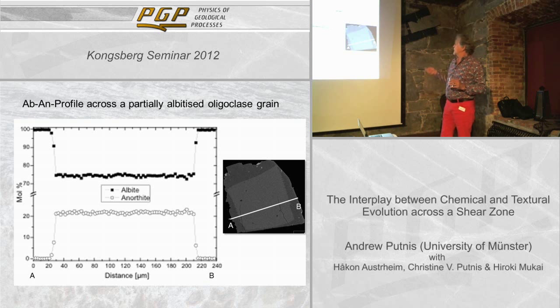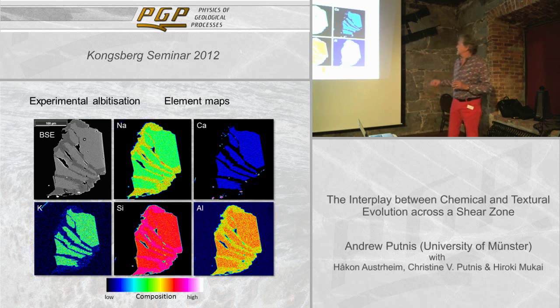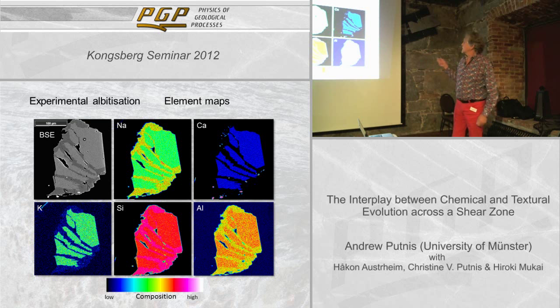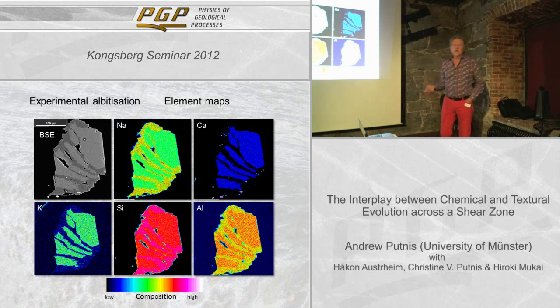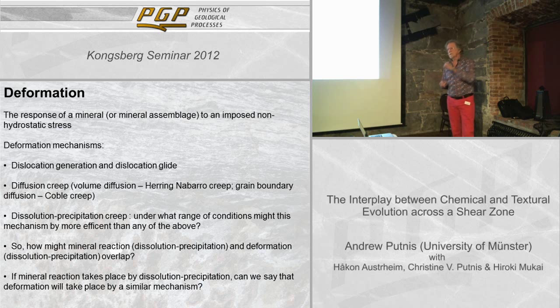Some experiments that Jörg Hövelmann did — you just take a nice gem-quality oligoclase, the calcium-bearing plagioclase, and heat it up at hydrothermal temperatures for a couple of weeks, and here is a partial reaction front. Geologically speaking, that's a twinkle of an eye — so these processes are fast. They're fast even in diagenesis: you can convert detrital plagioclase to albite at temperatures as low as 60 to 70 degrees. These reactions have very characteristic sharp boundaries — these are not diffusional fronts, it's actually a dissolution-precipitation front. And basically, by choosing the correct fluid, you can convert anything to anything, literally.